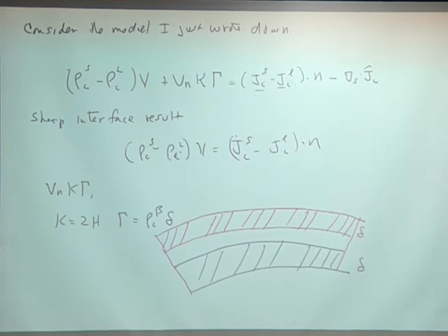So the mass, rather than just feeding the growth of the phases, feeds the growth of this interface because it's so thick. And in fact, it's clear that as the interface thickness goes to 0, that term disappears. And so if you want to use the realistic interface thickness of an alpha-beta interface or a solid-liquid interface, you won't have any problems. If you want to use an interface thickness that's on the order of microns, and the precipitates are on the order of 10 microns, this is a problem.